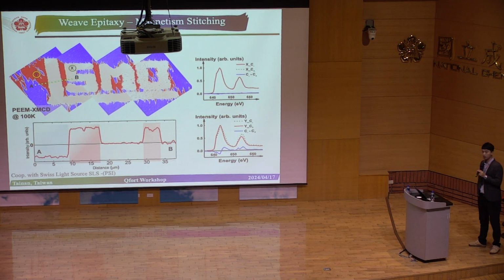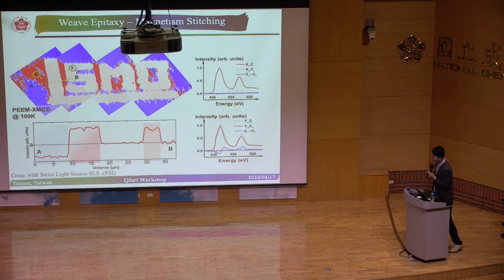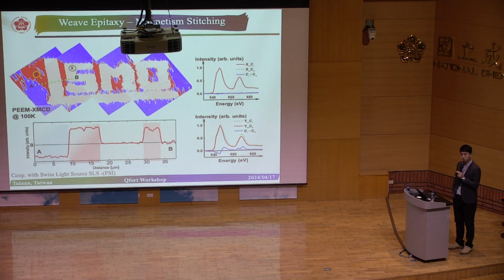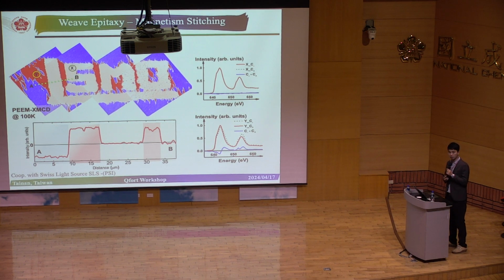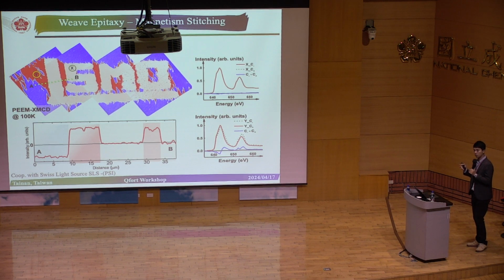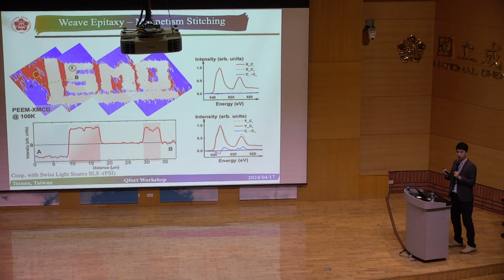So luckily we have some allies in Switzerland. A few of my students went to the Swiss Light Source. They spent a couple of weeks there and used a very advanced technique called photoemission electron microscopy, which can spatially reveal the magnetic contrast. In this picture, whatever you see in red and blue contrast is magnetic. The area with only very light contrast is non-magnetic. Through analysis of the spectra, you can also tell the configuration of the magnetization. So we hope to convince you that the inner side is anti-ferromagnetic, and the outer part, the matrix, is magnetic.